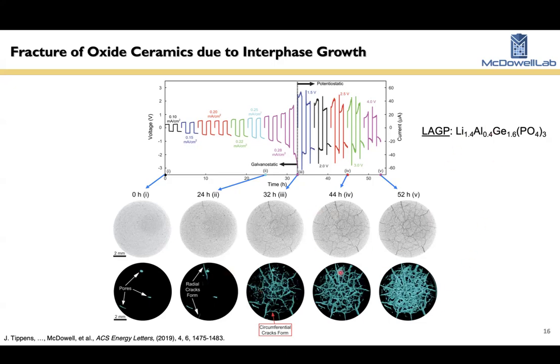And there's this volume expansion associated with the interphase formation. In this case, the interphase is quite thick, tens of microns or thicker. And this volume expansion induces stress in the ceramic and actually causes the ceramic itself to fracture. So these images here just show that these cracks are forming in this ceramic pellet. And the bottom row of images is the segmented fracture pattern.